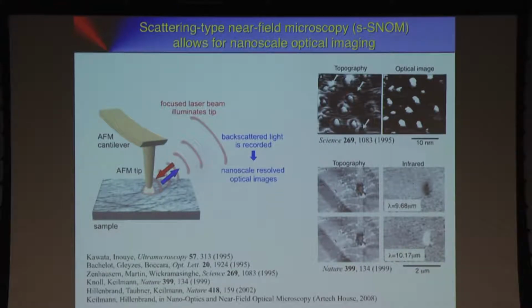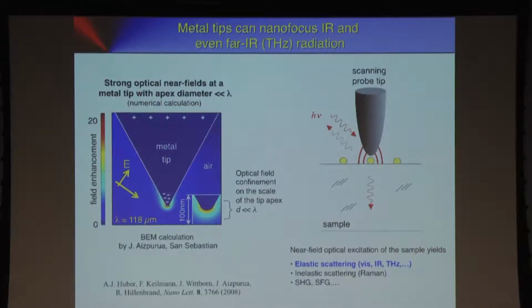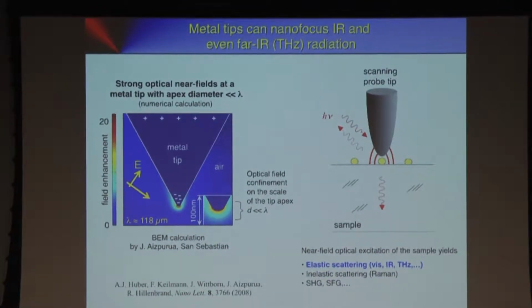I want to show you now what is the physics behind that and what is the technology we use. So that's a numerical simulation done by my colleague Javier Aizpurua in San Sebastian. It shows a metal cone here, 1 micrometer long, which is illuminated by a beam of 118 micrometer, that's terahertz, with a polarization that can be projected on this axis here. And what happens is that the terahertz field drives a current here. The current, of course, is oscillating here. Charges are squeezed into the tip apex with the terahertz frequencies. And that gives rise to a very strong field concentration, field enhancement.